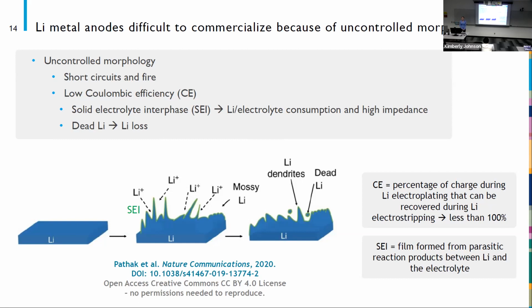And the reason that we don't get all of that back, and that Coulombic efficiency is below 100%, is because we form what's called the solid electrolyte interphase, or the SEI. The SEI is a film that's formed from parasitic reactions between the lithium metal and the electrolyte. And the electrolyte is not chemically or electrochemically stable with lithium metal. And so that's why we have this problem, but we like to operate in the voltage range that we do because it gives us higher energy density and higher voltage. So we're sort of stuck with this problem where we're unstable, but we really want the energy density that affords.